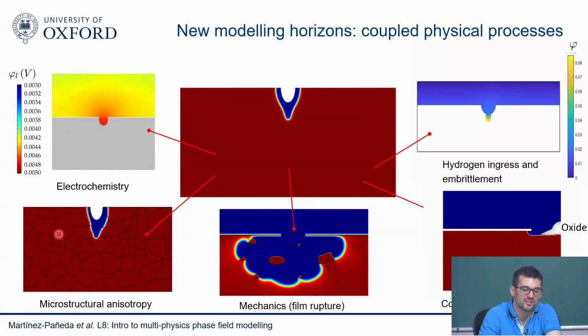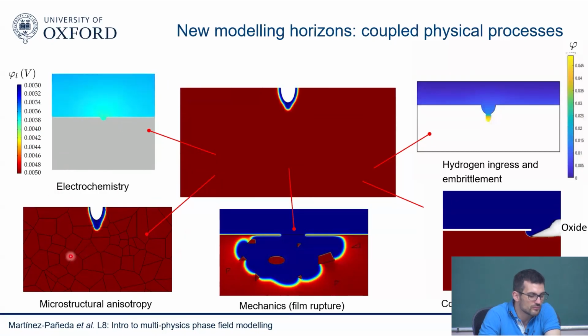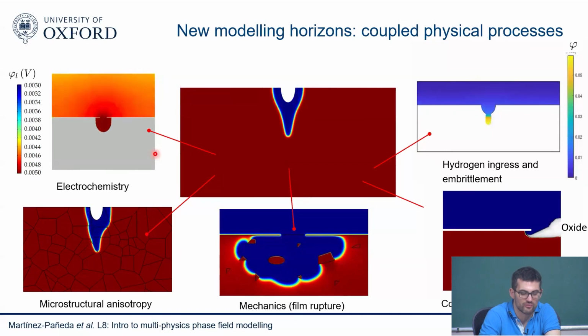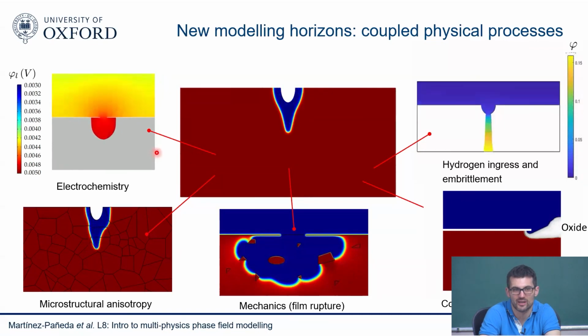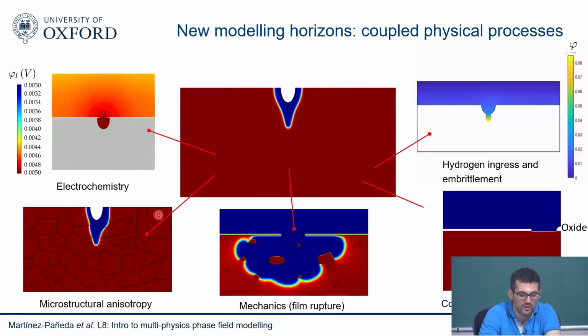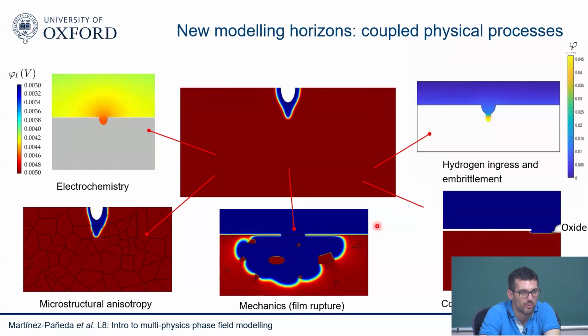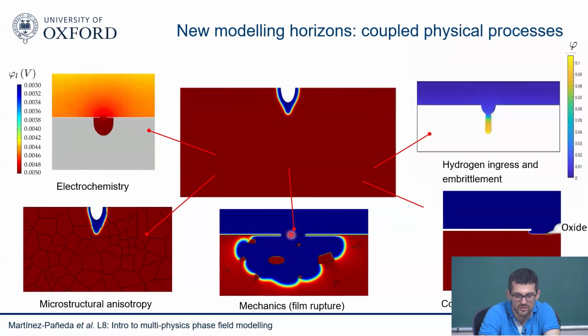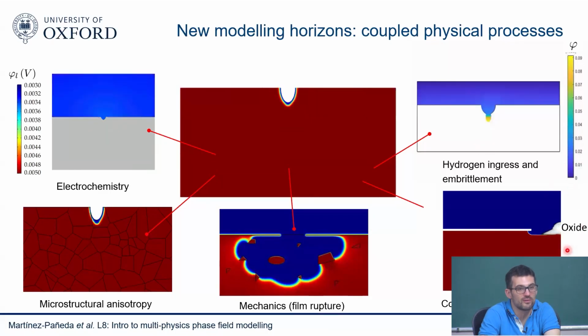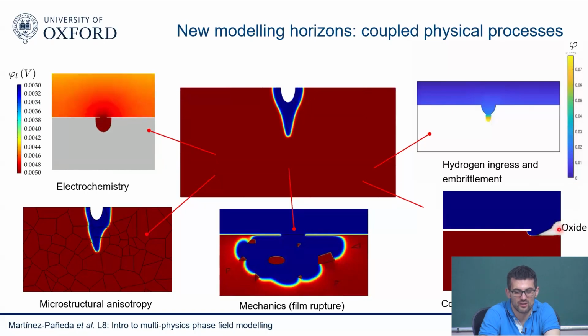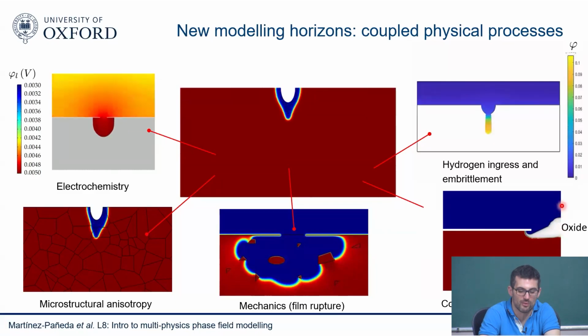Microstructure anisotropy can play a role, particularly when you're nucleating or growing a small pit. Again, you can incorporate this. You can solve this with different microstructure, with crystal plasticity. You can couple this with an EBSD map. You have mechanics as well. Of course, mechanics plays a big role in film rupture, but in other problems as well. You can also incorporate this. You may have other products forming. For example, as you see here, you form an oxide. You have corrosion product formation. And you can see that you can have an extra phase field. You can have as many phase field models as you want.